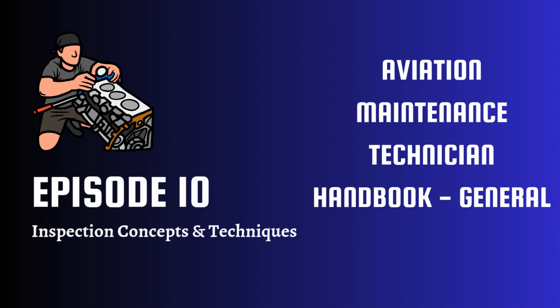Okay, MPI for steel. What about inspecting conductive materials that aren't magnetic, like aluminum or titanium? We mentioned eddy current inspection for heat damage. Right. Eddy current, sometimes called electromagnetic analysis or ET, is incredibly versatile. It's used on electrically conductive materials, which includes most metals used in aircraft. It can detect surface and subsurface cracks just below the surface, corrosion, especially hidden corrosion that causes material thinning, and as we discussed, it can also determine the material's alloy type or its heat treat condition.